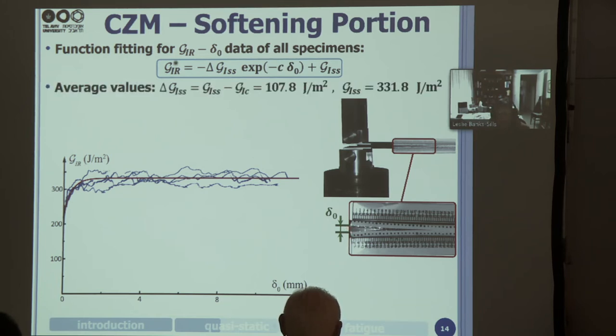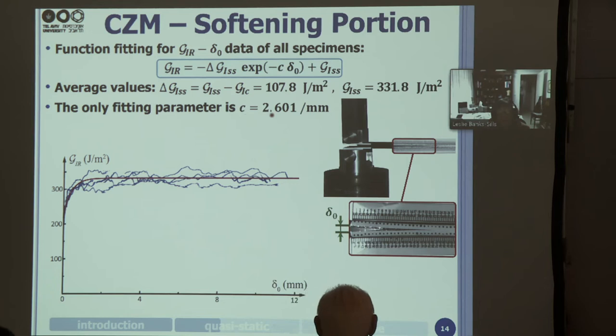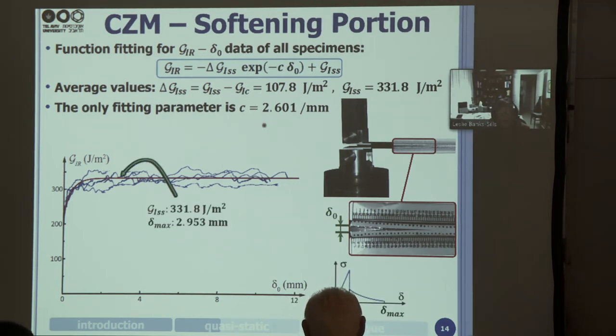And so we draw this curve. This is the red curve. And here is delta G1SS, and here is G1SS, and we get a fitting parameter, C is 2.601 per millimeter, and we can get delta max from this curve. When the red curve reaches 331.8 G1SS, that's our delta max. At that point, we say that fibers are going to begin to break.